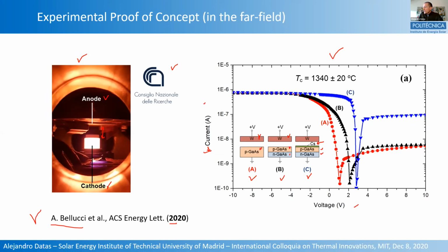And you can see that, well, in these IV curves, you see different things. First, this is the direct operation regime, where you can see that all devices have the same saturation current, so they can be compared. So in terms of thermionic current, they are identical. This other side is a reverse operation regime, where you see that these 2 devices have the same current because basically they have the same surface properties. So it's tungsten and P-type gallium arsenide in both cases. But in this other case, you have a higher reverse current, basically because you have this other anode surface treatment where you have cesium, and then you have a higher reverse current. So the current that goes from the anode to the cathode.